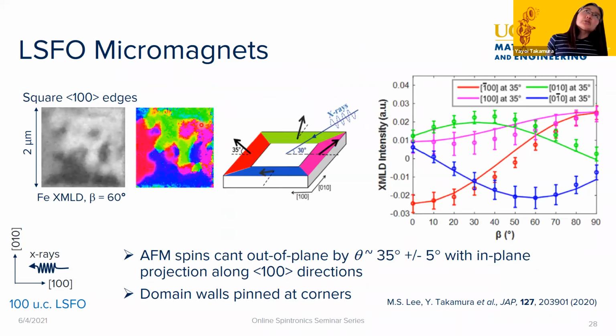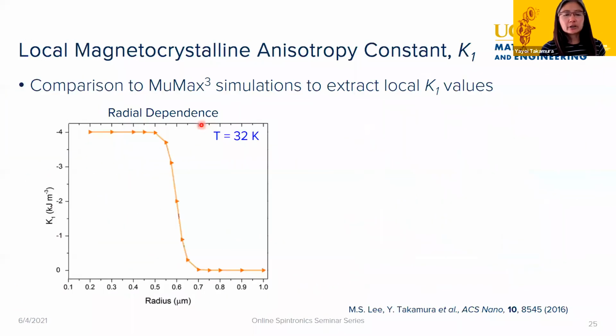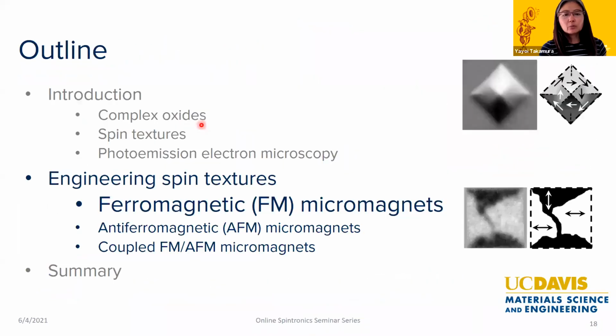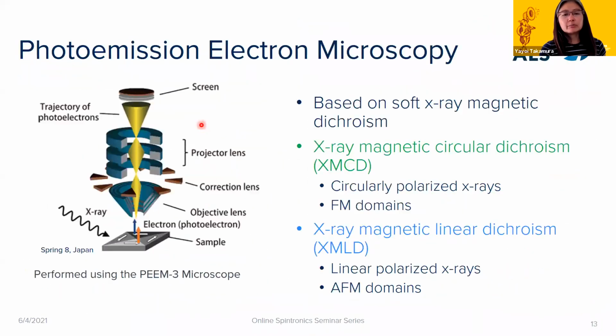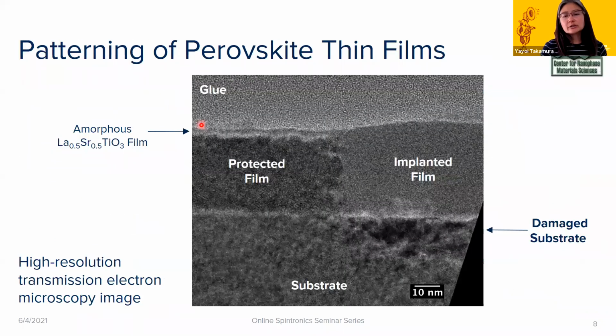One thing I should say is that magnetically, we don't really have a model, but going back to the question about the patterning effect, we think it might be because of the surrounding matrix that we have here, right? Because we have this implanted matrix, it's swelling up vertically, which also means it wants to swell laterally. So we think we're getting some kind of lateral strain field affecting the edge region, and maybe that's why we're getting an edge-induced effect.